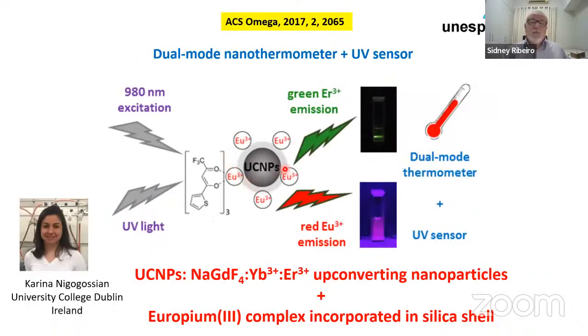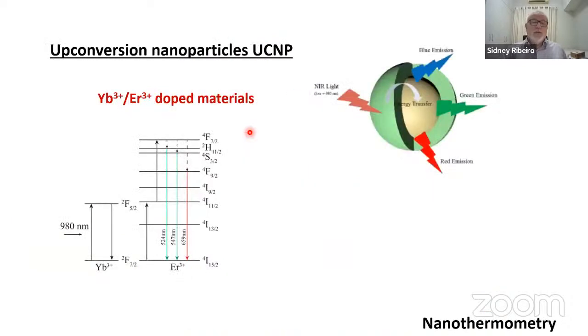You can play also with upconversion nanoparticles. I will come to this slide in a minute. Upconversion nanoparticles are particles made, for example, with ytterbium and erbium lanthanides. You have here the energy levels of the ytterbium and erbium. When you excite in the infrared at 980 nanometers, ytterbium will absorb the photons and will transfer to erbium in a successive way, addition of photons, populating high energy levels. So what you see here is that by exciting in the infrared, you observe emission from erbium in the red and in the green.